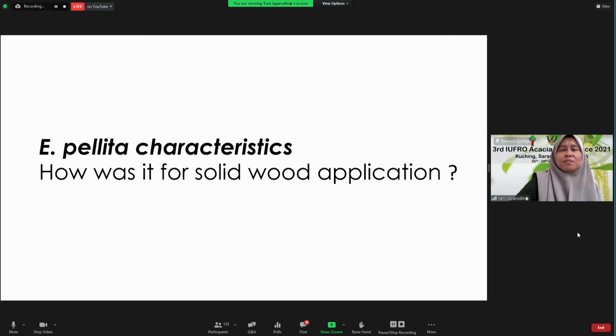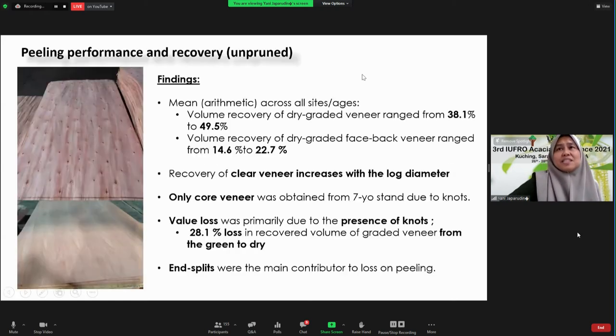How are the Eucalyptus pellita characteristics for solid wood application? So this is some of the findings that we found from our peeling study of unpruned material. This is the range of total volume recovery from the input volume. And this is the volume recovery of the face and back veneer from the total input volume. And we found that recovery of clear veneer increased with the log diameter. So only core veneer was obtained from 7 years old stand due to knots. And there is a significant percentage of loss of value because of the presence of knots from green to dry. And again, end splits were the main contributor to the loss on peeling.